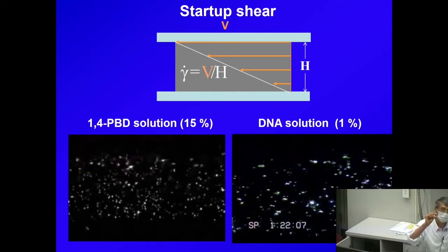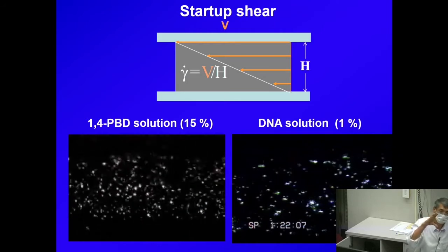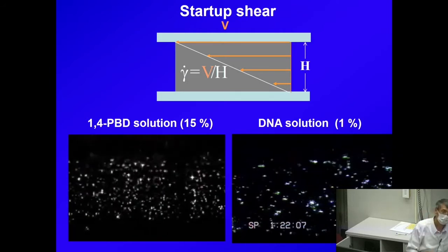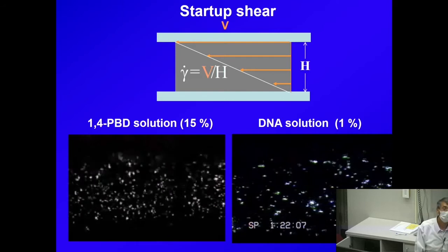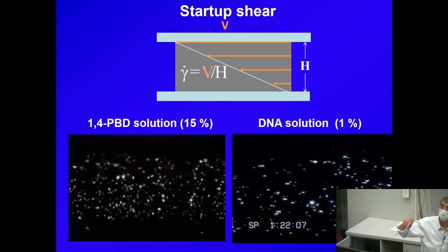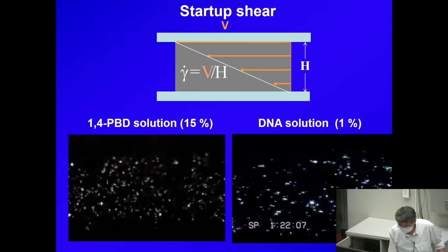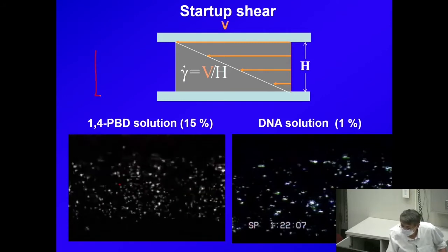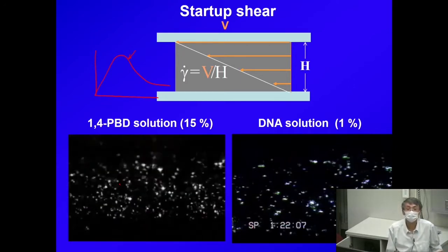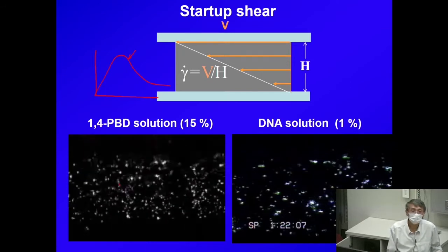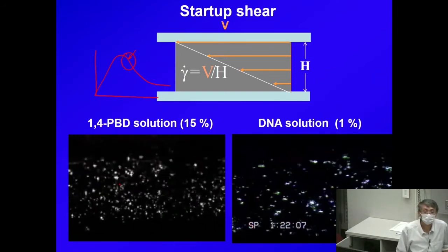It's a millimeter. If you don't use some magnifying objective, some kind of lens, to blow up this millimeter, you won't be able to see it. So you just need a microscope lens to observe it. The place it starts to break is right after the overshoot. This failure starts to occur right around here, right after the overshoot. This gives us all the insight you need: something is breaking apart after reaching overshoot, okay?